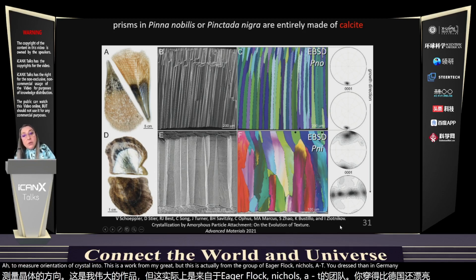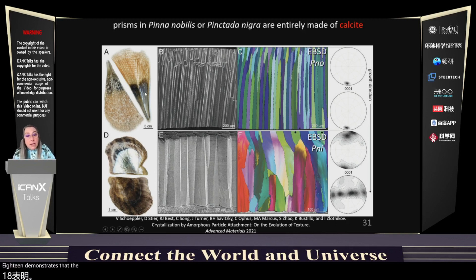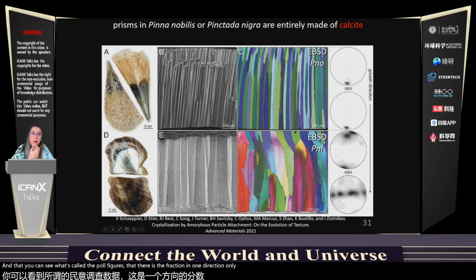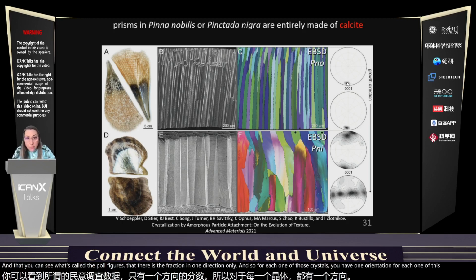And he demonstrates that in Pinna nobilis, each prism in the prismatic layer on the outside of the shell here is a single crystal of calcite. So each one has a single color. And you can see in what's called the pole figure that there's diffraction in one direction only. And so for each one of those crystals, you have one orientation. For each one of these prisms, you have one orientation. It's a single crystal of calcite.